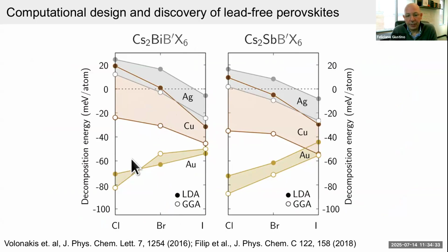So whenever these data points are below the 0, it means that the compound is unstable towards the decomposition into some byproducts of these kind of elements. And whenever the data points are above 0, it means that the compound does not want to decompose, and it will be stable. So what we learned from this, maybe just focusing on the left picture, is that whenever you have silver, you have some hope of replacing lead in these cases. And this will work most likely with bromine and chlorine because this is the region where we are mostly positive.